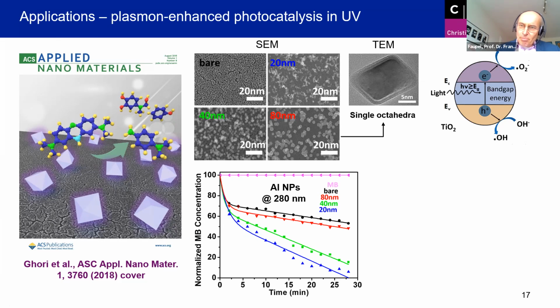We can simply test the activity by using test substances like methylene blue. And what you see here, this is a pristine titania, and this is a plasmonically enhanced titania where the decomposition occurs much faster.